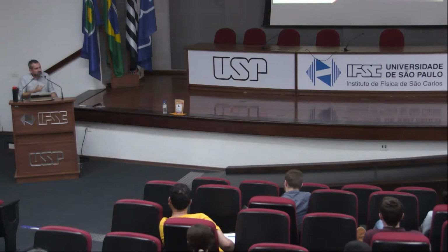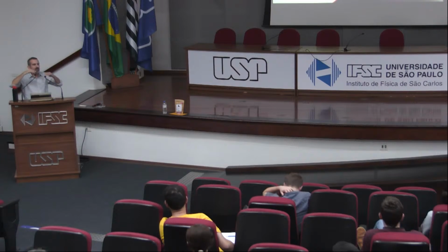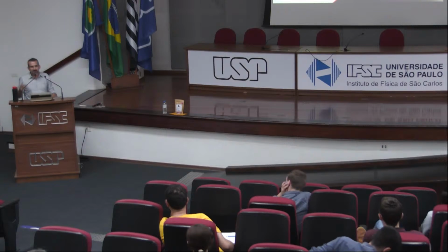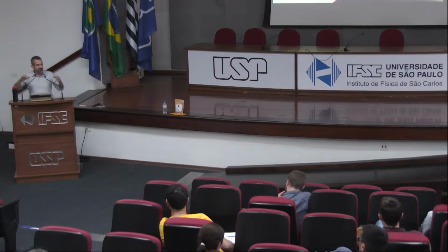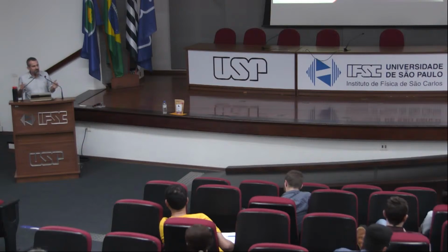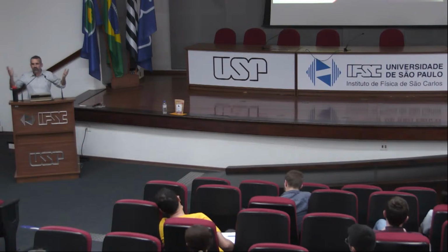And so these very slow modes on graphene, these very slow oscillations, we cannot get from ab initio molecular dynamics because we do not have time enough to allow for this simulation, and we cannot run them large enough. But if we make a large supercell and we let it run for a very long time, all the physics is there. And then we can see these very slow oscillation modes that we wouldn't get in the original ab initio calculation. Same thing for glasses, I understand. If you have some dynamics that is very slow, and you wouldn't get it in the standard picoseconds that we run, in principle, it should be there. You should get these modes from these trained potentials because you can leave the calculation running.